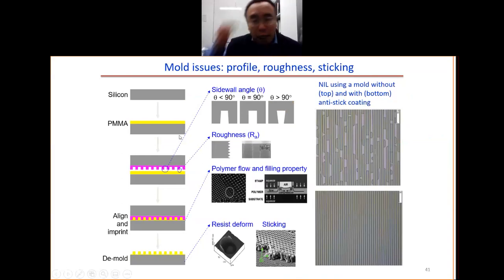So here are the mold issues. First, regarding the sidewall angle, this one will be difficult. When you do the imprint, it's very hard to separate. It will be like sticking. This one with vertical sidewall will be easier for the separation, but this one you lose the resolution. The feature size on the bottom is different from the feature size on the top. But this one is obviously easy to detach the mold from the wafer.